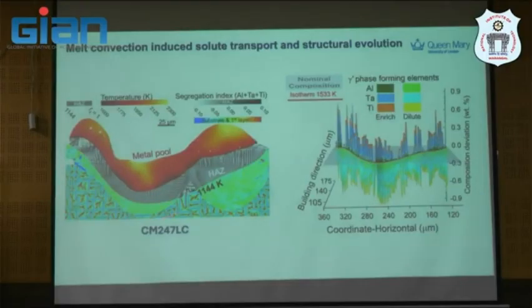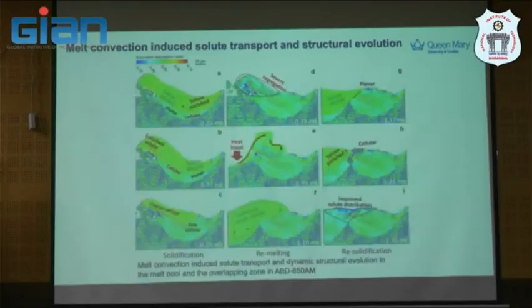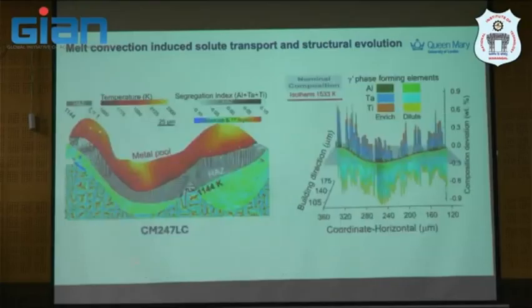What we see, what does it mean by that? If you see here, this is the melt pool, and you see the porosity as well. In CM247, if we move a little bit to the highly segregated kind of material like CM247, we talk about the hafnium profile. Again, this is coming from expert modeling only. So you will see this is the substrate layer and then the second layer here.